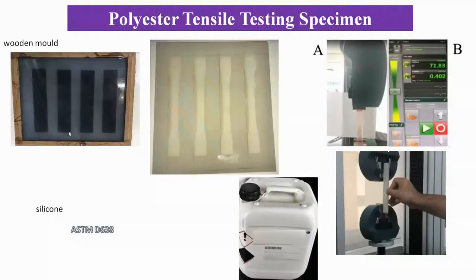In the process of studying fracture properties of the polymer, we need to know the tensile properties of the material. The next step is preparing the polyester tensile testing specimen. Over here, we use a silicone mold that has cavities of the same size and shape as the tensile testing specimen, based on ASTM D638. The silicone mold itself is made with the help of a wooden mold. The mixing ratio of hardener to resin is 1.5% for the polyester that we use. During the mixing process, we make sure that no bubble is introduced to the specimen. After curing, we use the specimen for the tensile testing as shown in the right-hand side picture.